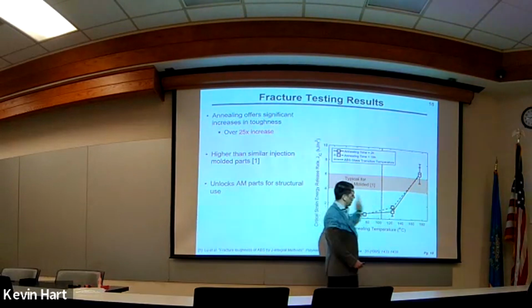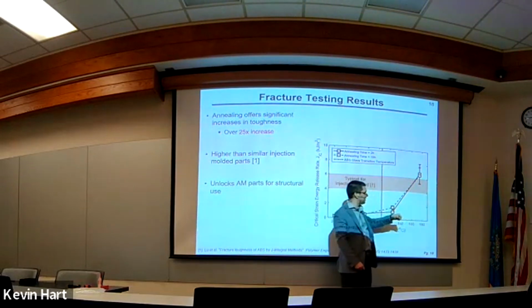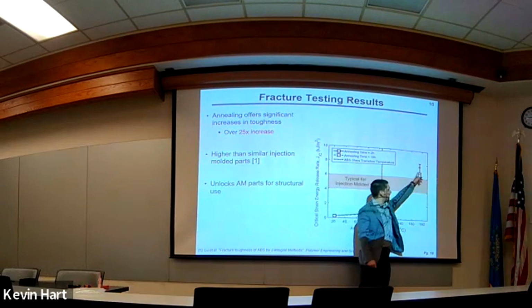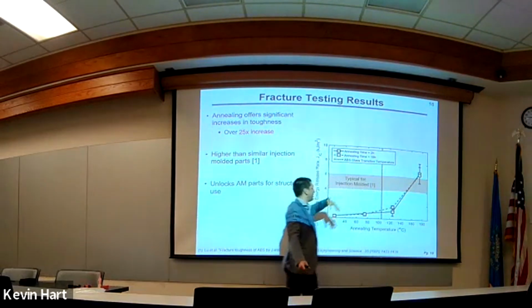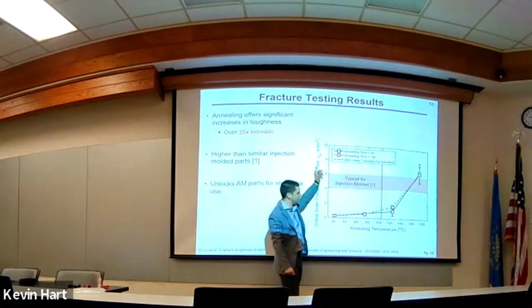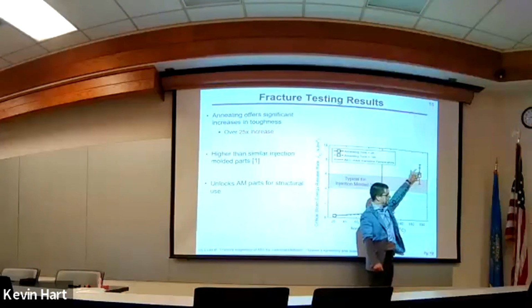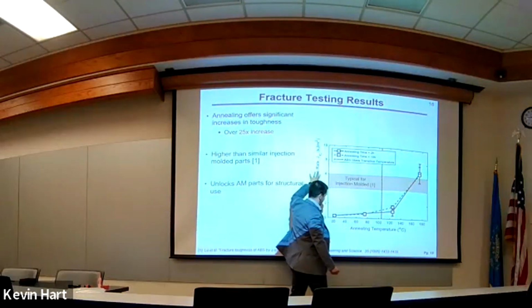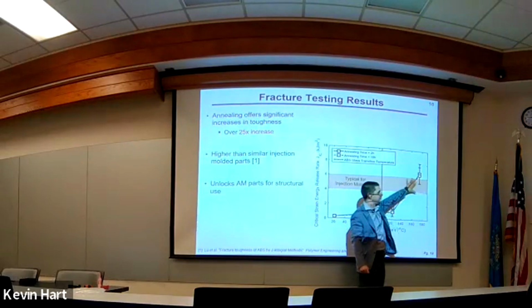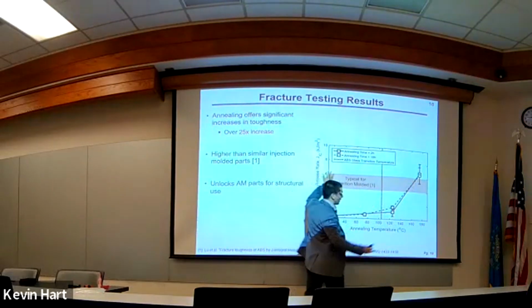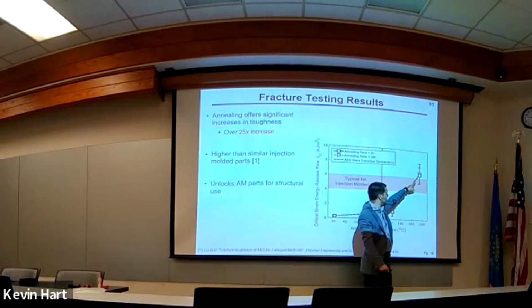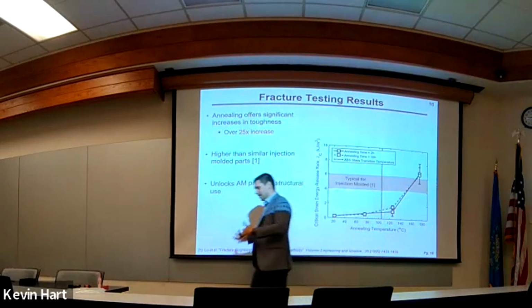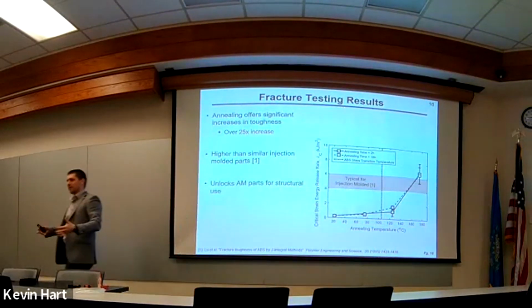But if you really blast this thing, go up to 175 C, you'll start to get toughness values here of 6,500 joules per meter squared, right? So 6 kilojoules per meter squared, and beyond. So this is your injection molded strength that we talked about before, 4,000 to 6,000 at the inner layer, or for a fully dense material. And now if we anneal, we get levels that are equal to or greater than injection molding.